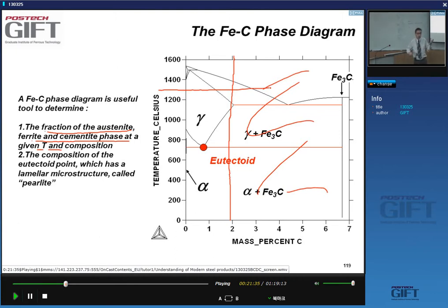you're also usually, with steel products, limited in your interest to the solid, when you reheat it after it's been cast and you're going to process it. And usually this reheating process is at 1300 degrees C or less. So you typically reheat your steels in this zone. So you basically are left with a piece of the phase diagram, the iron-rich corner of the iron-carbon diagram that we're actually going to look at in practice.